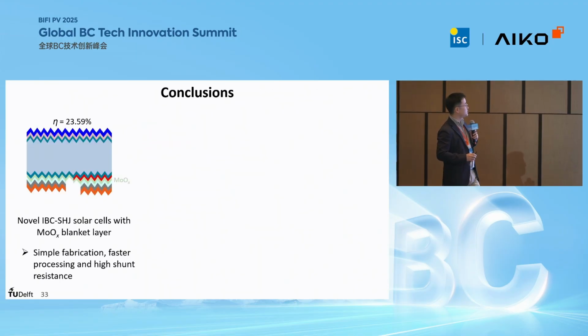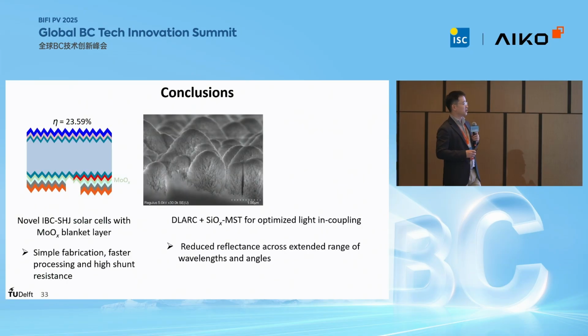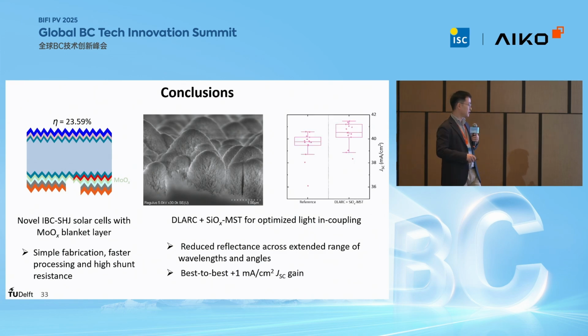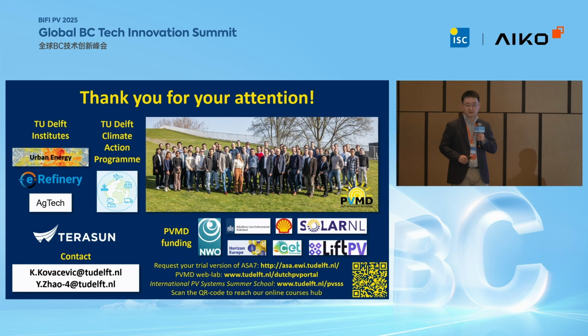So in conclusion, here I presented novel IBC silicon heterojunction solar cells with molybdenum oxide blanket layer, which features simpler fabrication, faster processing, and also high shunt resistance. And also I presented a double-layer anti-reflecting coating plus a silicon oxide modulated surface texturing to optimize the light incoupling. This reduced reflectance across an extended range of wavelengths and also angles. And last but not least, we showed the best-to-best more than 1 milliamp per square centimeter JSC gain with such an optical design. So with this, I'd like to thank you for your attention.